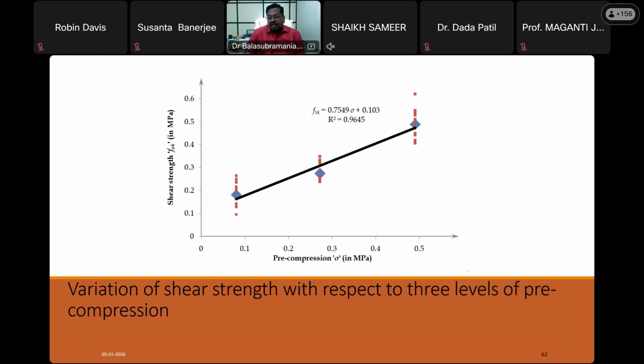Yeah, this is the shear strength result. We carried out this shear strength test with 3 levels of pre-compression, like here: 1, 2, and 3. Then we obtained this failure envelope, this black line, no? And the intercept we can obtain. The intercept is nothing but the shear bond strength, and the slope is nothing but the bed joint friction coefficient. The 0.103 is the shear bond strength and 0.75 is the typically estimated one.